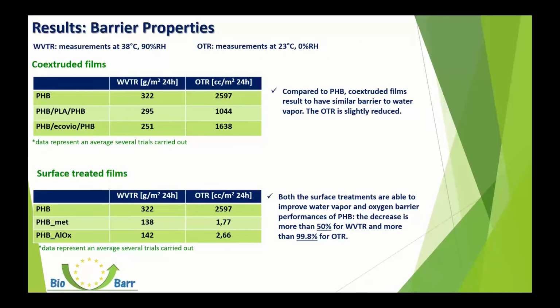Instead, for the characterization of barrier properties, the water vapor transmission rate was measured at tropical conditions, while oxygen transmission rate was measured at dry condition. It's possible to observe, as both PLA and EcoVio are not barrier polymers, compared to PHB, the co-extruded film results to have similar barrier properties to water vapor, and just a slight reduction of the value of oxygen transmission rate, which is still very high.